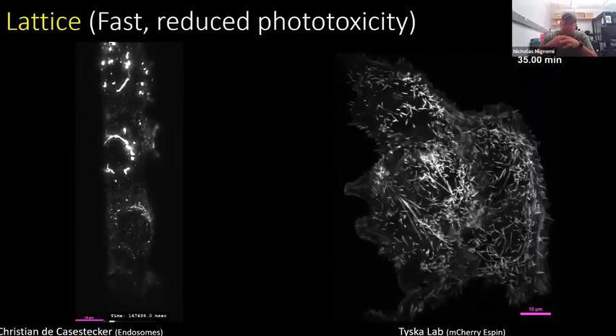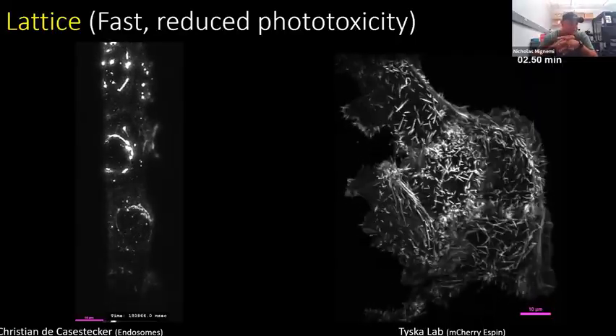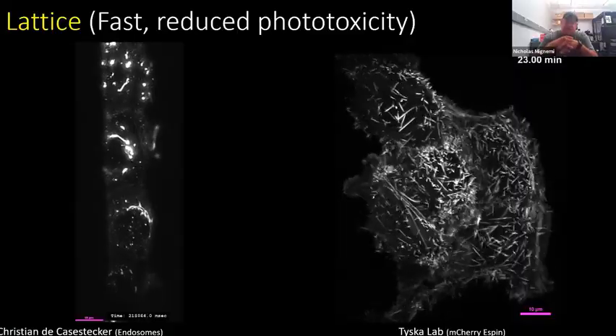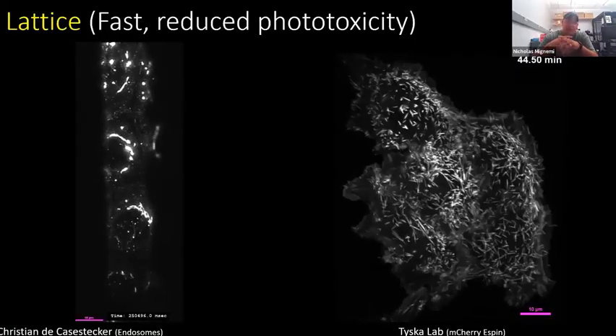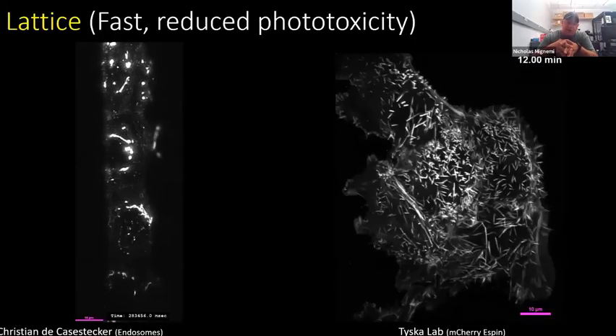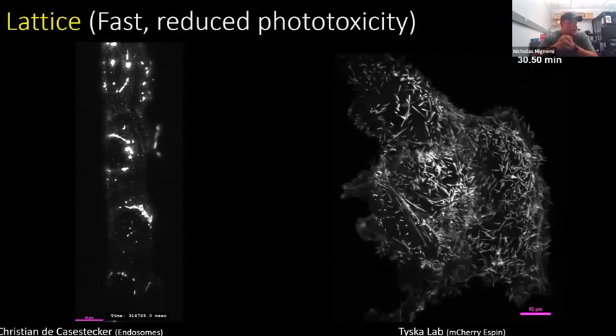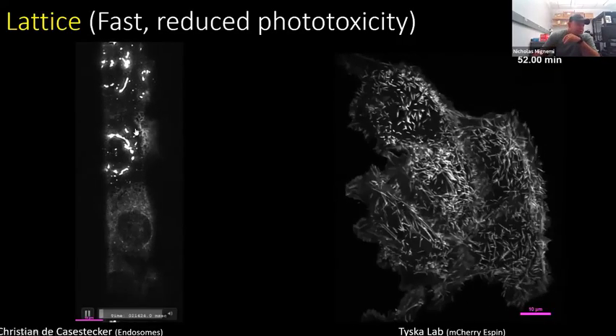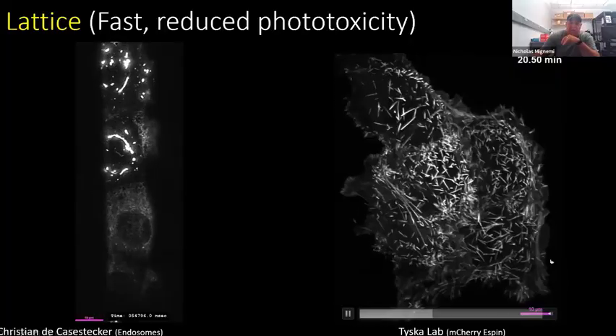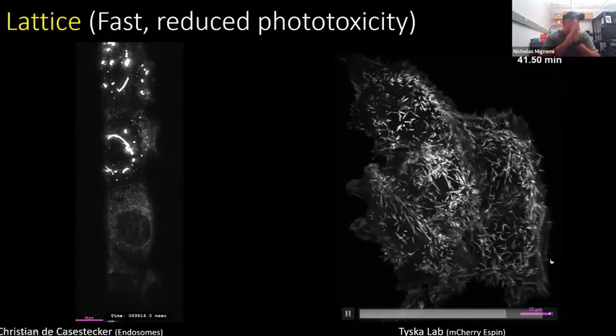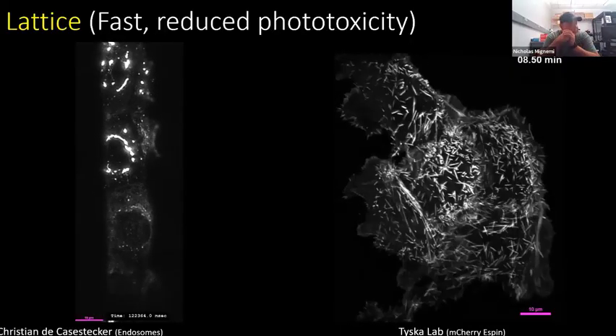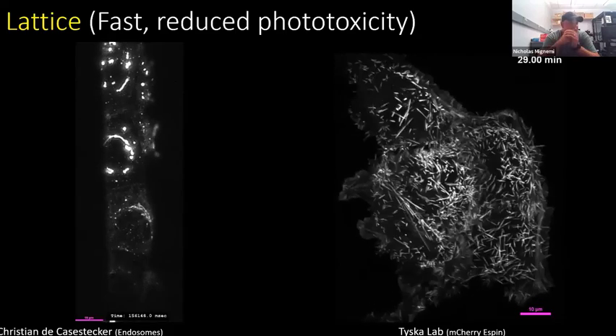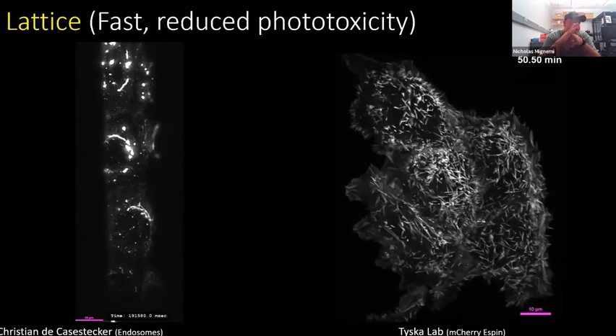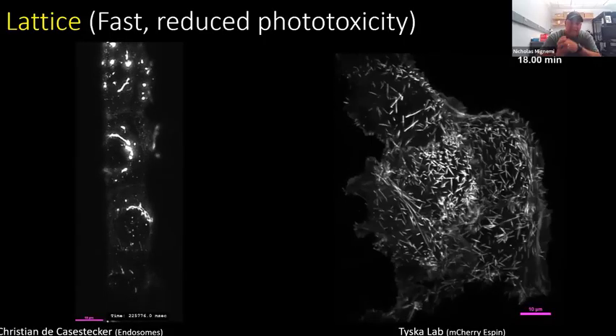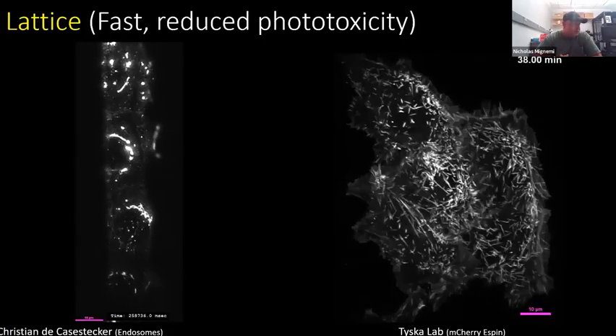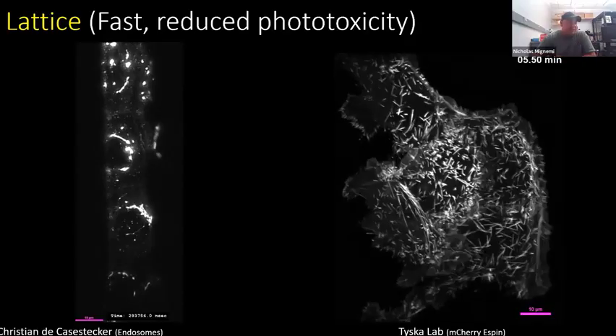Previously, we were getting a lot of people interested in this particular topic because the Lattice is so fast. We can image at volume, and we're able to track some of these functions that occur. They're particularly interested in how these little tiny dots, which are whipping around our cells here, are moving out to the apical membrane. This image here is captured just shy of our maximum speed of about half a second, or 500 milliseconds, per cell volume. And this data is in 3D.